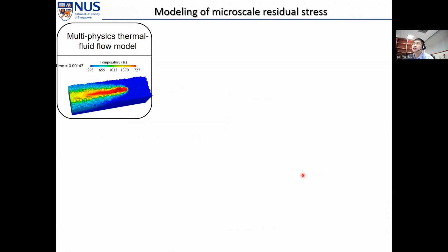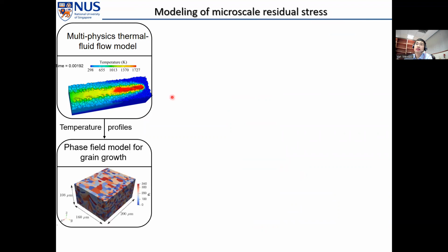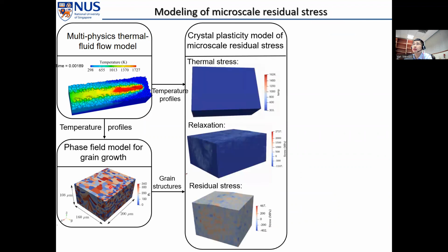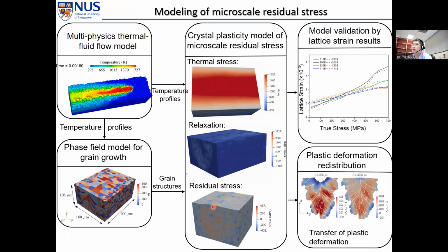And in an even smaller scale, in grain scale, actually the thermal stress or residual stress varies across different grains. And this is the origin of micro cracks. To address this challenge, we implement both the temperature profile and grain structure into a crystal plasticity model to simulate the micro-scale residual stress. And also we consider the cooling process where the thermal stress will be relaxed into the residual stress, and we compare with the experimental results in literature.